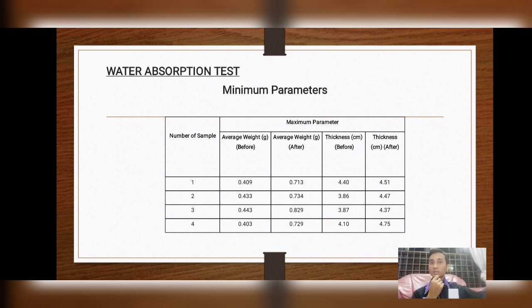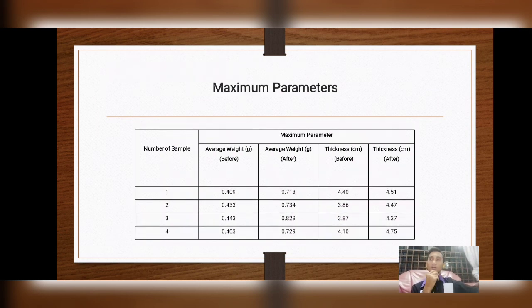From 0.3 gram it turned into 0.7 gram, which caused a difference of 0.4 gram between before and after the experiment. And also the thickness of the sample increased from 4.6 cm to 5.49 cm, making it thicker than before the test began. For the maximum parameters, the weight also increased from 0.4 gram to 0.7 gram, a difference of 0.3 gram. The thickness also changed a bit from 4.4 cm to 4.5 cm.